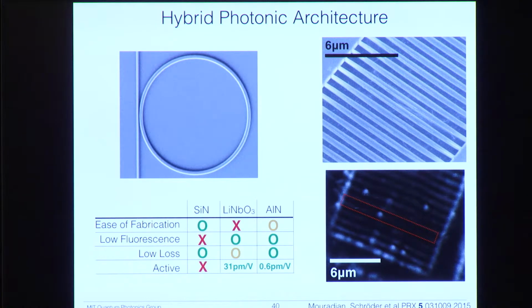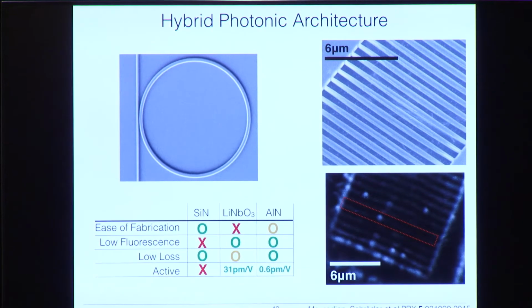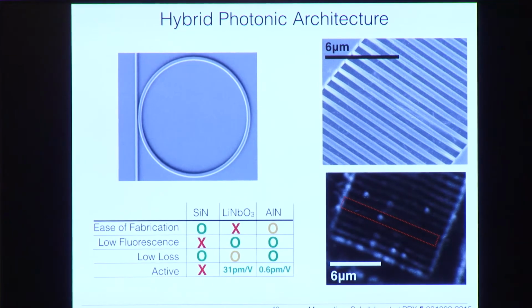There are also other options. So what we need out of a photonic backbone platform is we need it to be easy to fabricate, so that silicon nitride was. We also need it to be low loss in the visible, so the three that we considered were silicon nitride, lithium niobate, and aluminum nitride, although there could be others. We would like it to have low background fluorescence, since we're going to be shooting a fair amount of optical power through these waveguides. Unfortunately, as you'll see, silicon nitride is not low fluorescence. It has a lot of defects, not pure crystalline, whereas lithium niobate and aluminum nitride both are low fluorescence.